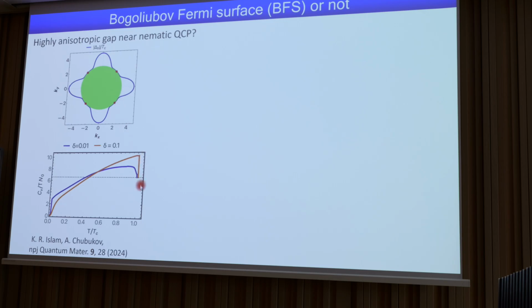And then if you measure specific heat, you can actually get a very large value until you reach a very low temperature. That's his suggestion, but this is actually coming from the strong nematic fluctuations.